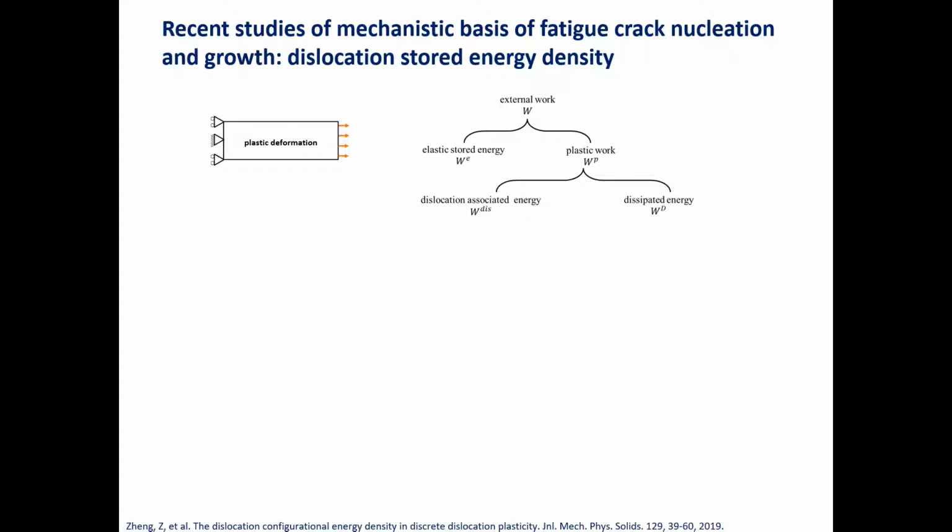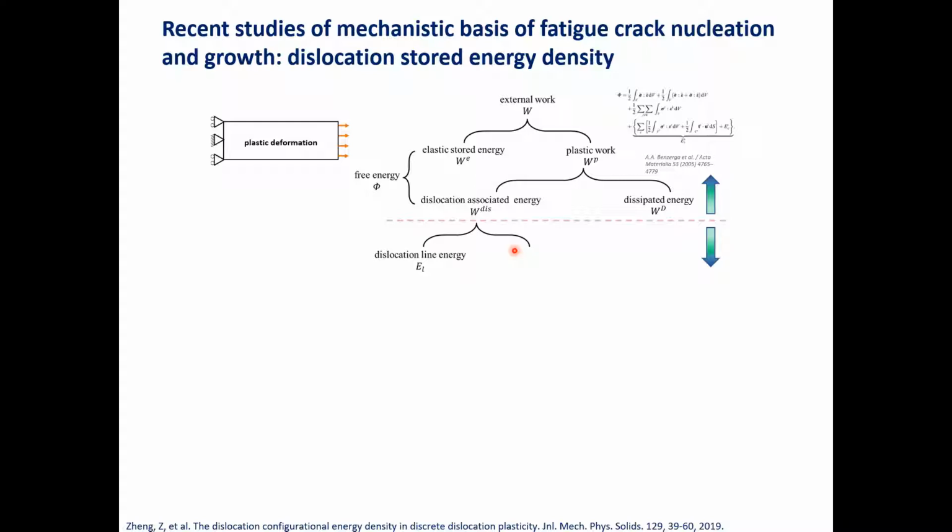and growth. So I will not dwell on this very much because I'm going to move on to higher level methods, but the overall approach is to recognise that we have stored energy elastically, which is recoverable. We also have energy associated with the dislocation structures, and those dislocation structures we can to some extent calculate and quantify the energy associated with them, but the energy is there, free energy, to drive potentially crack nucleation and growth. So in terms of the dislocations, some of that energy is just the individual line energy associated with discrete separate dislocations, so that's not relevant to us.